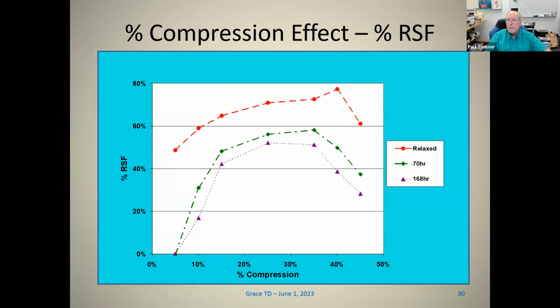Additionally, you can look at the effect of percent compression to determine the optimum percent compression. In this case, it shows the percent retained sealing force, and it shows that at low percent compression, you get lower sealing force, which makes sense, but you actually lose it faster.